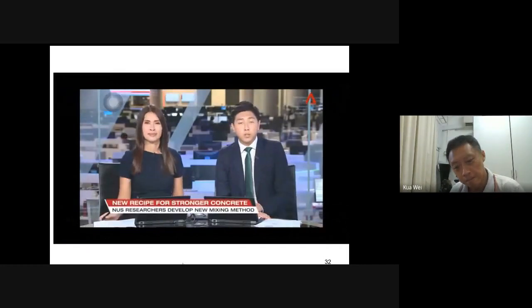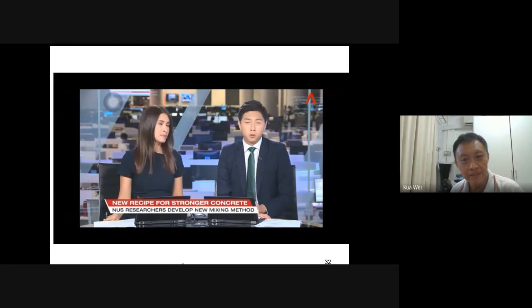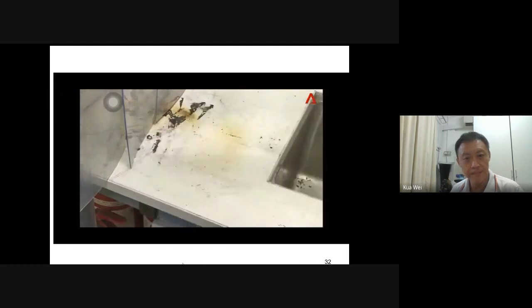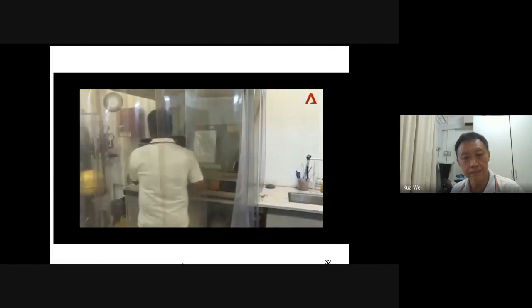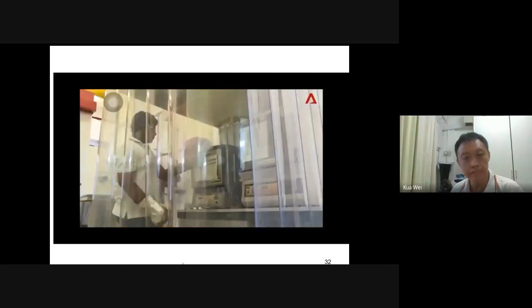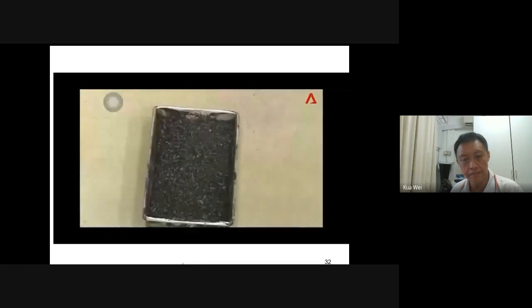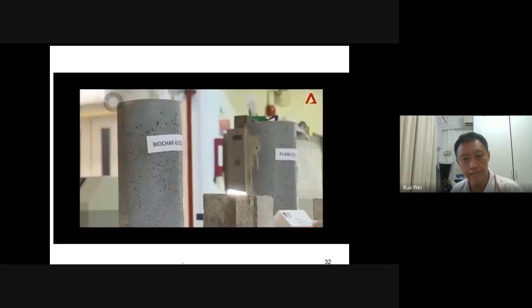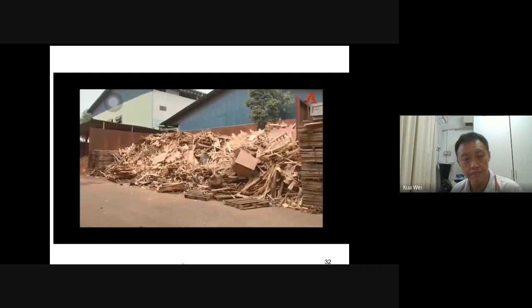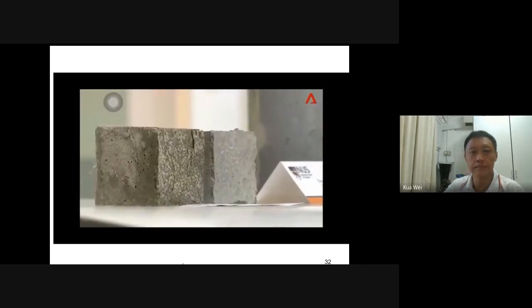Concrete could actually make buildings more durable. They would also be more environmentally friendly because it puts wood that would otherwise be disposed of to good use. Vanessa Lim with more. It's an ingredient for a recipe that will make concrete stronger. This tray of sawdust is going to be cooked under heat and converted into a special type of charcoal, which can help to improve the mixing process for concrete. And it's environmentally friendly because no carbon dioxide is produced. Called biochar, the charcoal has many holes on its surface, which means that water can be easily absorbed and retained. While they are smaller than a fingernail, these shavings can help to create concrete structures 20% stronger than those made without it. Beyond making buildings safer, the new concrete mixing method could also help to put wood waste to good use as it recycles sawdust from it. By strengthening the concrete mixture, items could be made thinner and lighter while still retaining their strength, resulting in less concrete being used.